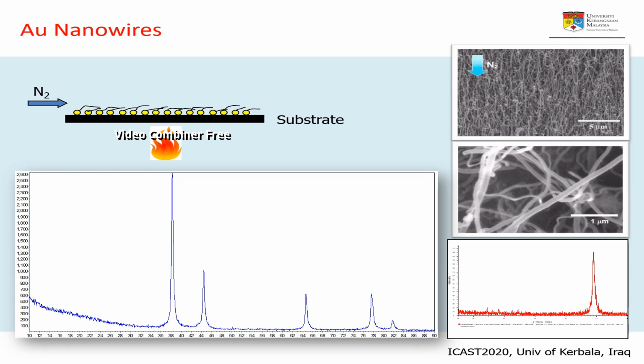Using sputtering technique, a thin layer of gold was deposited onto a silicon substrate. Then, the film was heated in a tube furnace in flowing nitrogen gas. Finally, the film was characterized using field emission scanning electron microscope and X-ray diffraction technique. As you can see, the top right-hand side FESEM images confirm the formation of nanowires, which are generally aligned along the direction of nitrogen flow.